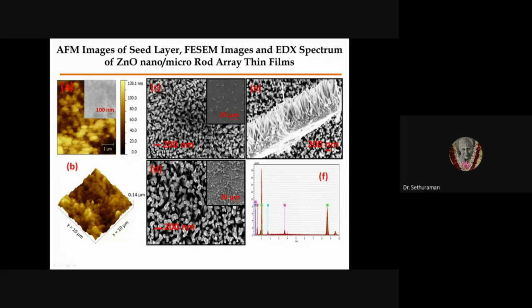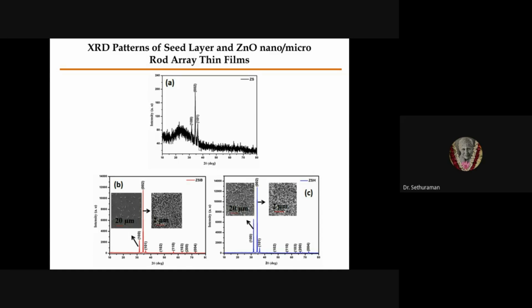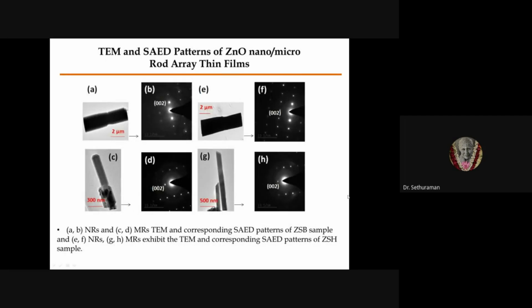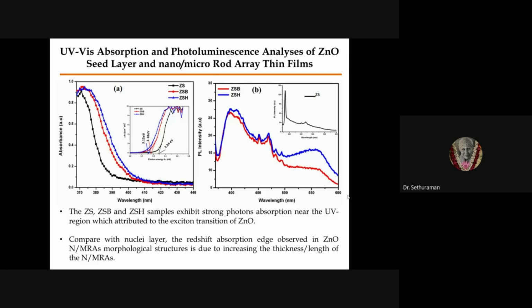All samples are prepared on the surface of a glass substrate. From the XRD we confirm that the seed layer has 002 orientation as the dominant one, and we found the 002 crystallographic orientation for the zinc oxide nanorods grown by chemical bath deposition. In the hydrothermal technique also, the 002 crystallographic orientation of the zinc oxide nanorods is dominant. So we compare the crystallographic pattern and the nanorod thickness, and everything is confirmed by TEM and SAED patterns of the zinc oxide nano micro rod assembly.